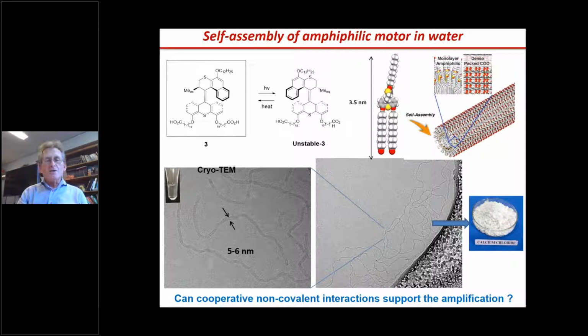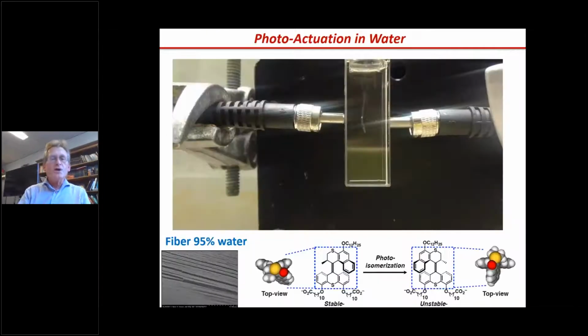They indeed assemble in water. You see these nice structures, these 5 to 6 nanometer type fibers. And then we use the trick, calcium, and calcium binds to the carboxylates and assembles these fibers into nice muscles. And what you see here in the lower corner, you see this alignment of all these fibers.